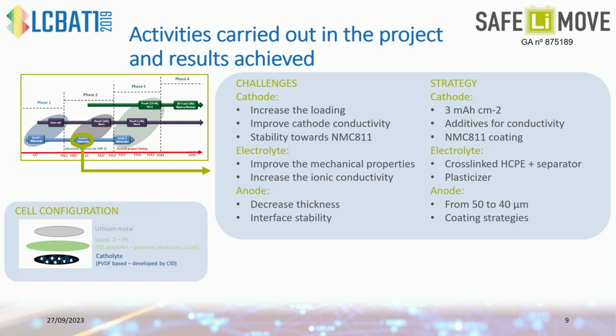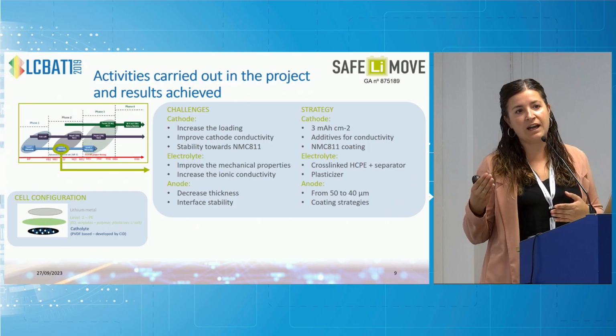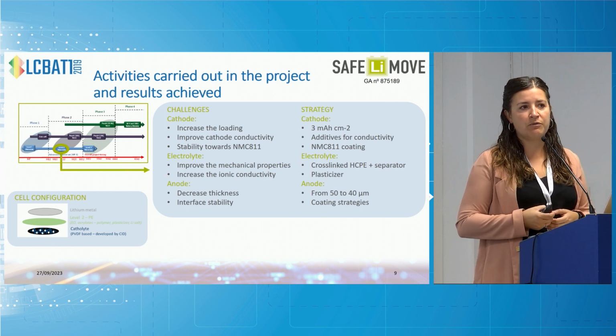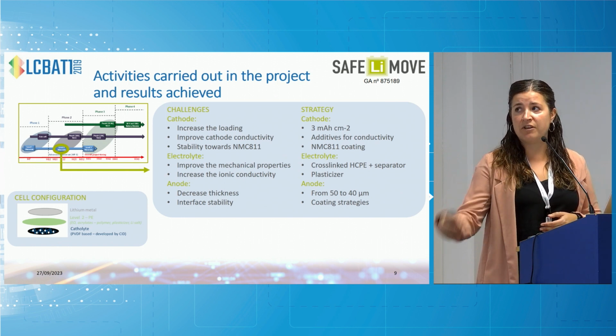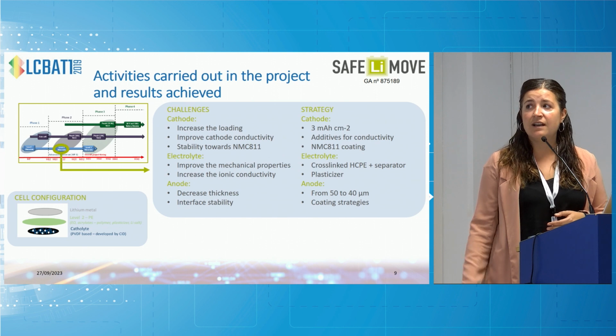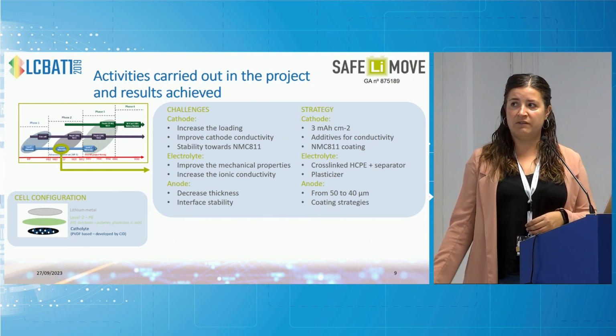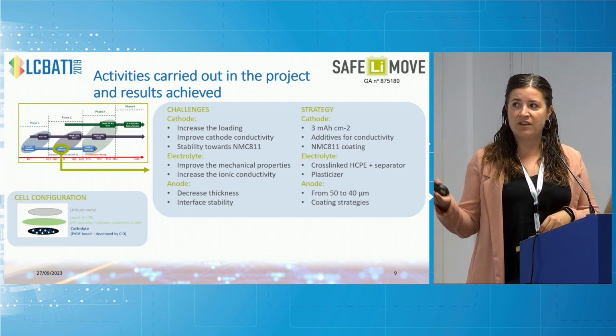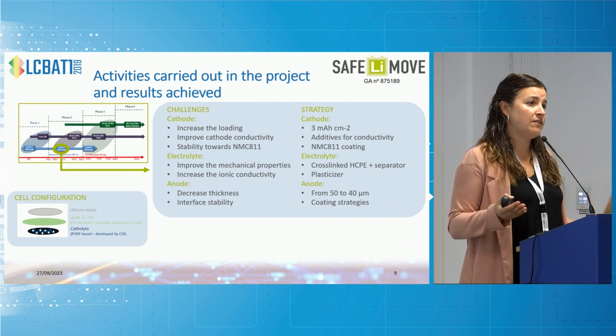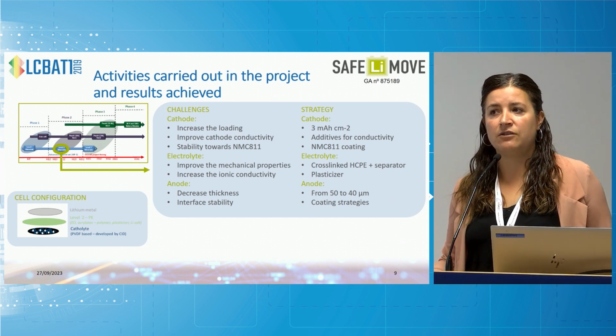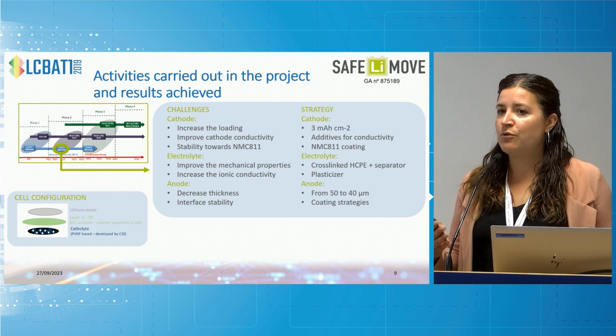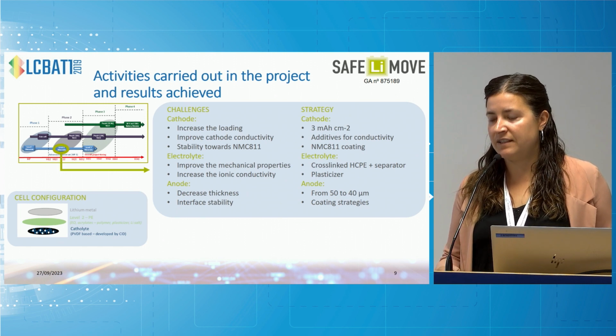If we consider the electrolyte, one of the challenges that we found, actually was found by CIDETEC when they were trying to scale up, was the lack of enough mechanical properties. So this will have an issue on the handling, but also will have an issue when we are talking about the battery operation to avoid the propagation of lithium dendrites. And we needed to increase the ionic conductivity. And then considering the third component, the anode, we needed to decrease the thickness because this will have an impact on the energy density, but also we were looking for improved interface stabilities.